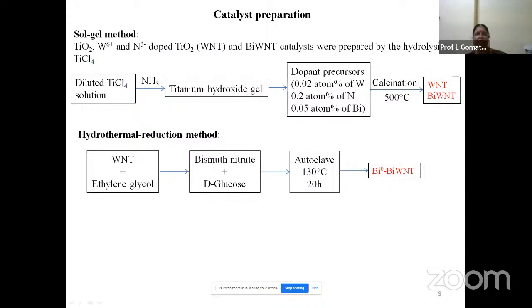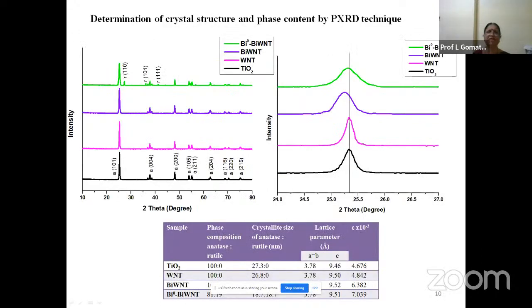In the case of the hydrothermal reduction method, WNT, that is tungsten and nitrogen doped TiO2, is taken along with ethylene glycol. To this, we add bismuth nitrate, and it is taken in an autoclave and heated at 130 degrees centigrade for 20 hours. And in this case, as I mentioned earlier, both bismuth 3+ and bismuth 5+ get incorporated, and part of the bismuth exists in a metallic state on the surface of the catalyst.